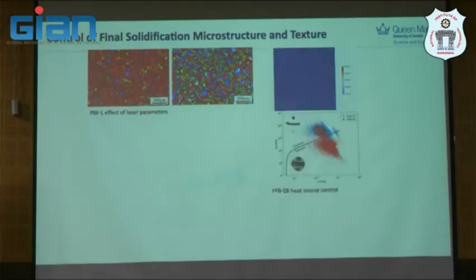But in order to do that, because people try to do rapid calculation, this is an example from Professor Babu at Knoxville, at Oak Ridge. Can't remember the full names, but you will see this aluminum alloy, trying to predict the columnar to equiaxed transition here. And then just wait a second, you will see how the melt pool actually looks on a large scale here. This is more like a reduced order model, that they can predict the likelihood of the region where you will see a larger melt pool or smaller melt pool. And each dot represents the printing area. So you can map roughly from the thermal model the G over R, so you can extract the microstructure approximately.